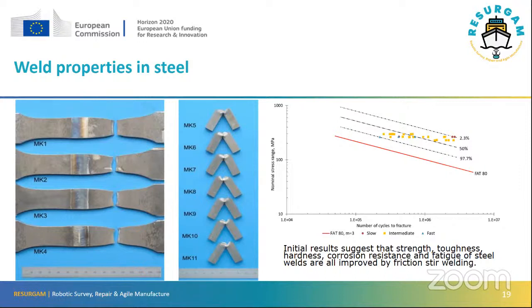And then the graph on the right-hand side of the screen shows one of the Lloyd's Register acceptance tests for fatigue. And all the friction stir welding that we did was above that red line, which was the acceptance criteria that was set by Lloyd's for this particular example of work. And so it seems to be that friction stir in steel gives a stronger weld, a tougher weld, and a much more fatigue resistant weld than the competing processes.